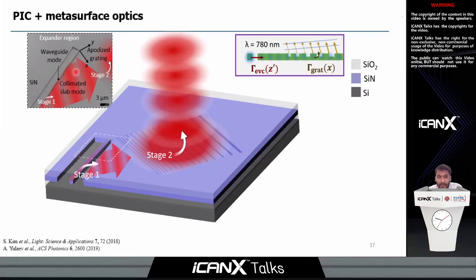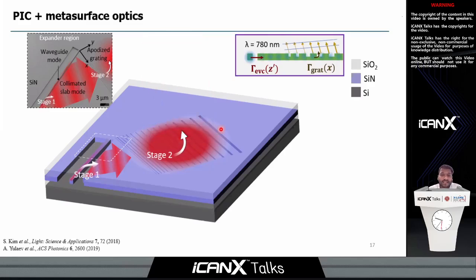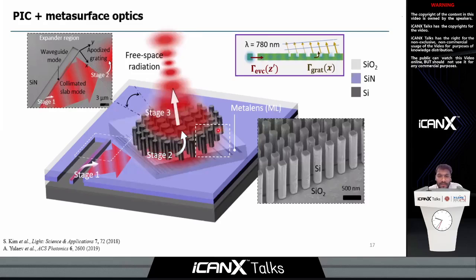So now you have adiabatically expanded this beam in one dimension, and then if you hit an apodized grating and look at the beam coming out, what you have is a beam that is hundreds of microns in diameter, going from hundreds of nanometers in diameter, with a very well-controlled polarization, in this case linear, and a very well-controlled directionality given by the pitch of the grating. But what really enables the functionality is the metasurface aspect, where we showed that if we make a metasurface directly on a second-layer lithography, or we bond a metasurface chip directly to the top of this extreme mode converter, then you can leverage all the capabilities of a metasurface, such as changing phase, polarization, directionality, divergence, and whatnot, that a metasurface enables one to do.